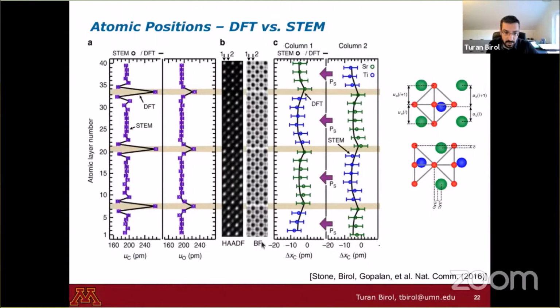So the 2 columns here are the scanning transmission electron microscopy data, where on the left you see individual atoms or columns of atoms, and the brighter ones are strontiums, and the less bright ones are the titaniums. Oxygens don't show up in this setting, but on the image on the right, in the bright field, ABF image, the darker spots you see are the oxygen positions. So this is really cool. Experimentalists can really see the positions of these atoms, which still impresses me each time I look at a STEM picture. But what you cannot see with the naked eye is that the center of these atomic unit cells, when you look at oxygens versus the cations, are shifted with respect to each other by a little bit.